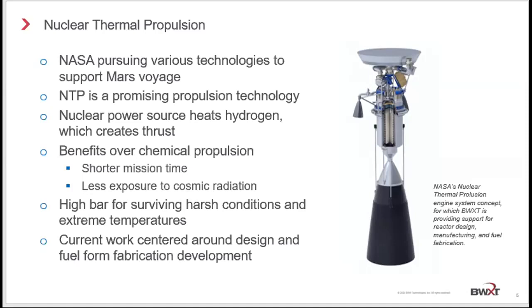You've got significant pressure differentials that you have to survive, as well as temperature differences that you have to survive just to reach steady state. And steady state's only 10 to 15 minutes long, and then you shut the reactor off, cool it off, and you're effectively in a coast phase. So the manufacture of fuels that can achieve those temperatures and survive the hysteresis of that temperature differential is going to pose some significant manufacturing challenges. And those are the challenges that BWXT, NASA, DOE are working through today.